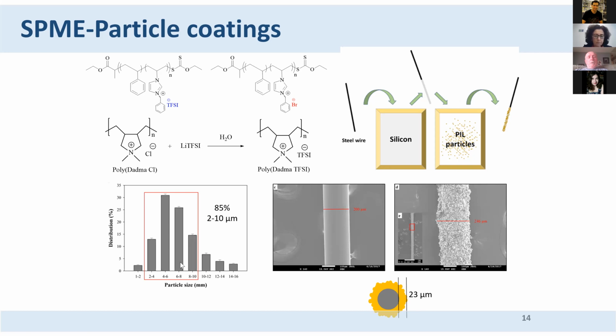And this was a very interesting work because it was very simple. So the particles had a size between 2 and 10 microns, and you can see here the wire before coating and the wire after coating. You can see that the increase was 46 microns, which divided by 2 is around 23 microns. But here we have the surface area effect.